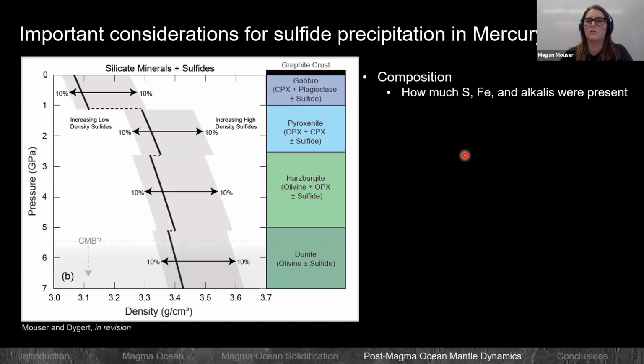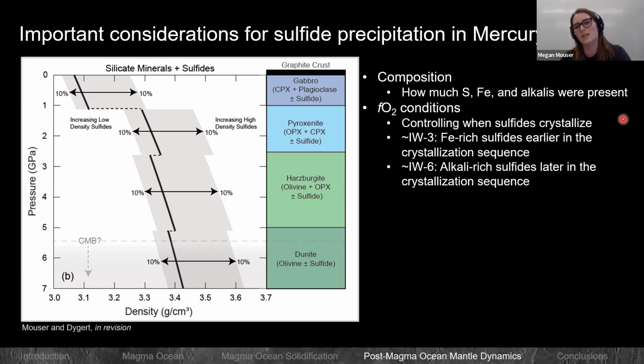First, of course, composition is the first consideration: how much sulfur was present in Mercury's interior? Was there enough to have a significant amount of sulfur in there? And additionally, if you did have something like an iron-bearing sulfide, how much iron was there? Because we don't see a lot of it on the surface. Does that mean it's locked up in these sulfides, or there just wasn't much in the silicate composition to begin with? And of course, the alkalis, because this is important for some of those lower density sulfides. So how much of all of these are present is the first question that we should be asking ourselves.